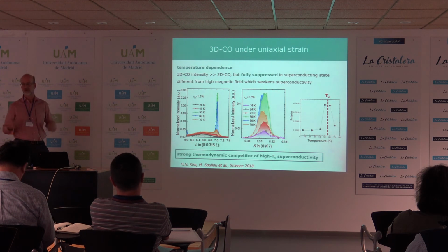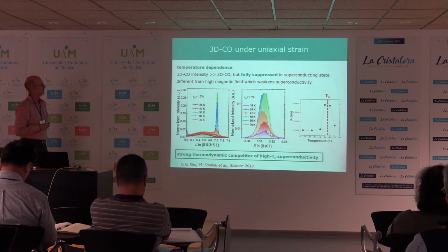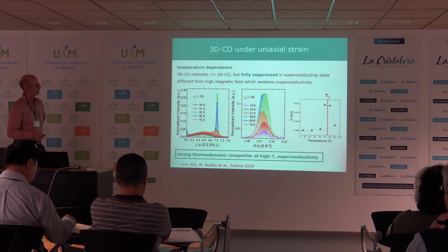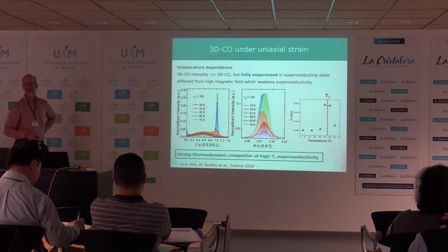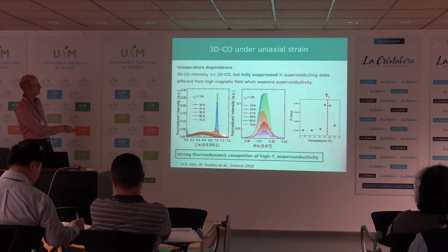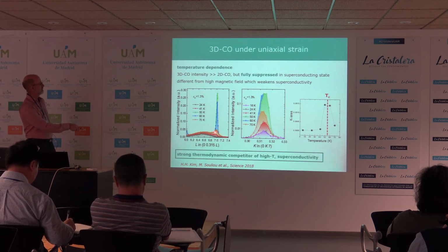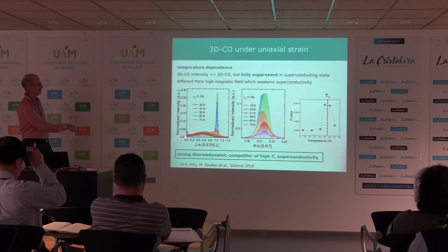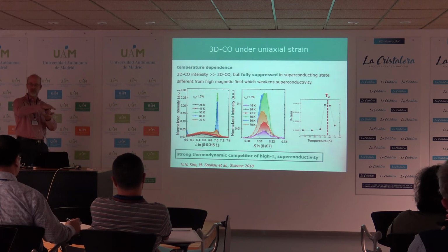It does its regular thing. But the 3D charge order is extremely strong. And when it goes superconducting, only the 3D one disappears, but the 2D one stays. Yes, exactly. So that's actually shown here, in the superconducting state at finite strain. So here at 24 Kelvin, this peak is completely gone, but the rod, which is modulated due to these intra-bilayer correlations, is still there.